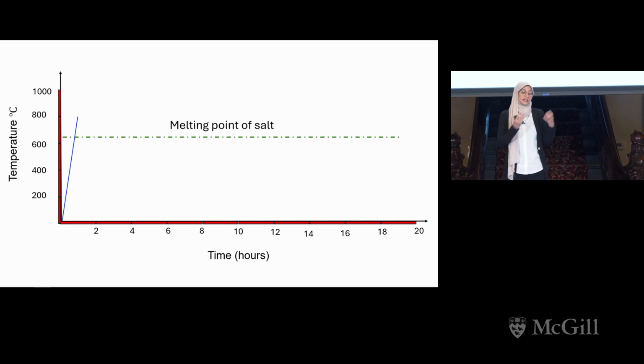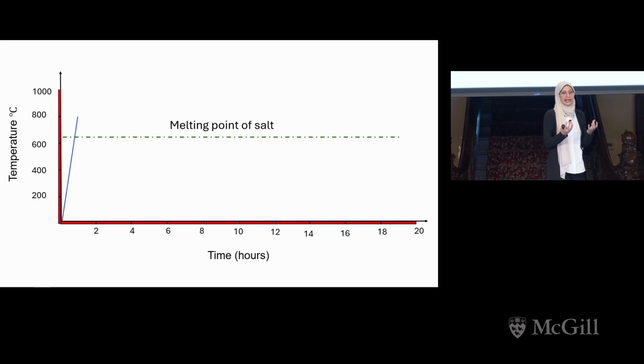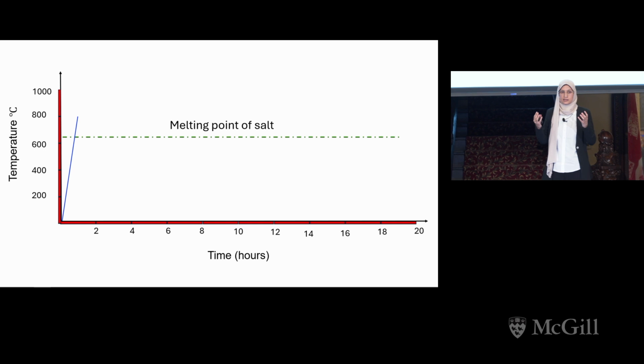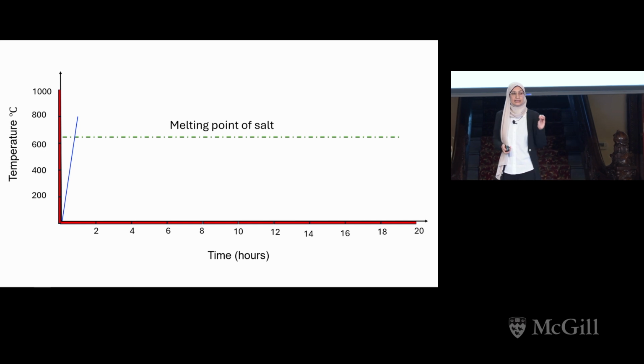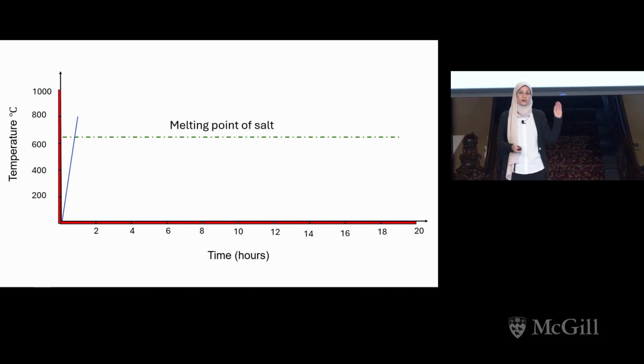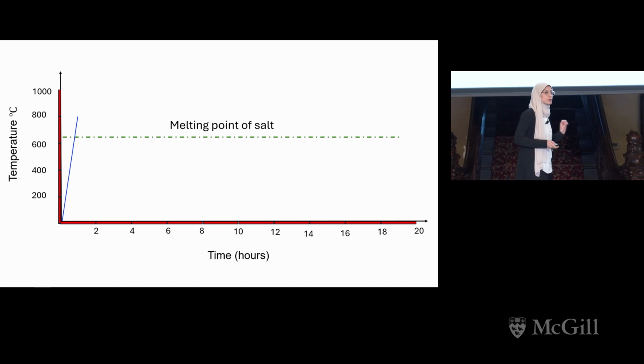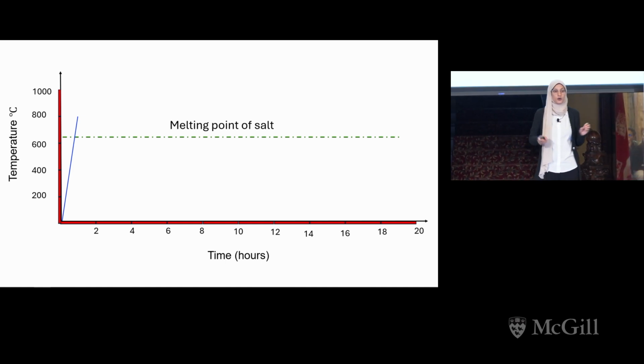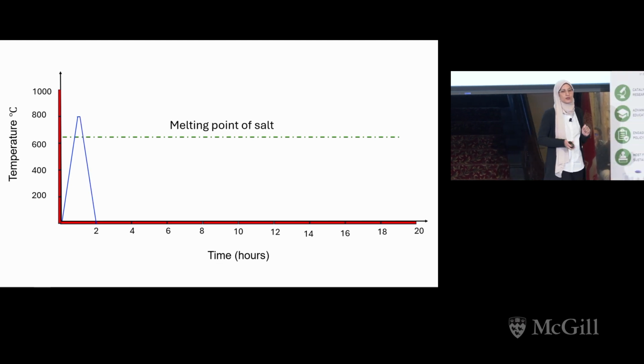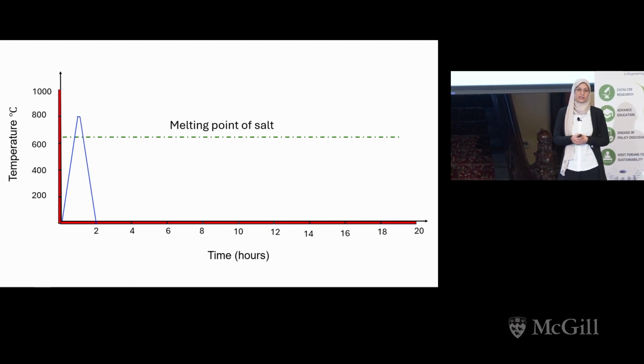So we transform the solid-solid reaction to a liquid-liquid reaction. Everything now is ions, and this will speed up the reaction. Therefore, we were able to reduce the reaction synthesis temperature from 1000 C to 800 C, and also reduce the reaction time from 12 hours to 1 minute. So after 1 minute, we immediately stop the reaction by cooling down the furnace.